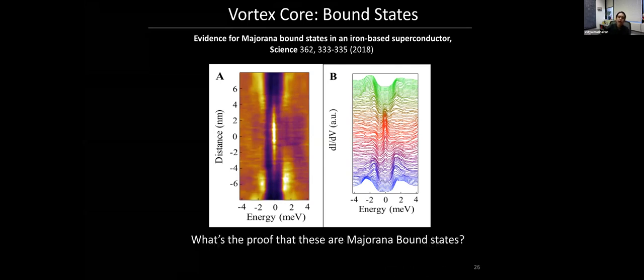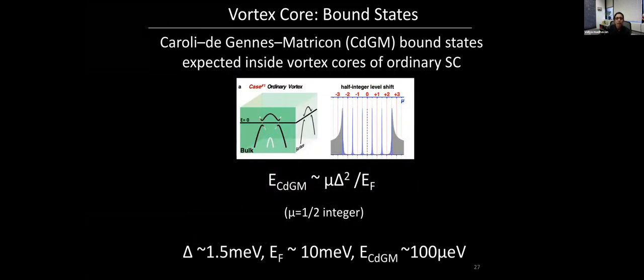And then one can ask, okay, you can see zero bias states. You actually see zero bias vortex core states even in niobium diselenide. The question is, what is the proof that these are actually Majorana bound states? In fact, one knows that you should see Caroli-de Gennes-Matricon bound states, which are just regular bound states inside a vortex core, even for an ordinary superconductor. Now you can ask the question, how do you distinguish these Caroli-de Gennes-Matricon bound states from Majorana bound states?